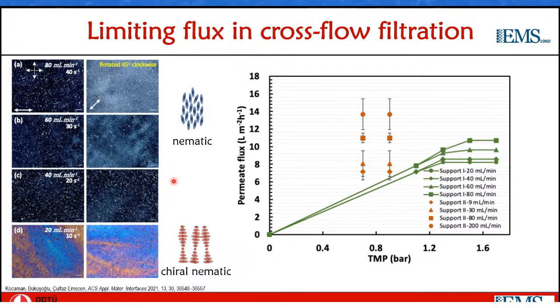These are the polarized optical microscope images on the transparent support at increasing cross-flow rates. So what we see is that indeed by increasing the cross-flow rate, increasing the shear that the nanocrystals are exposed to, we see a larger difference in light intensity between the image taken at the same direction as the flow direction, as is here, and when the flow direction was 45 degrees to the polarizer and the analyzer. And this difference is actually indicating a higher extent of alignment into what's defined as a nematic alignment for liquid